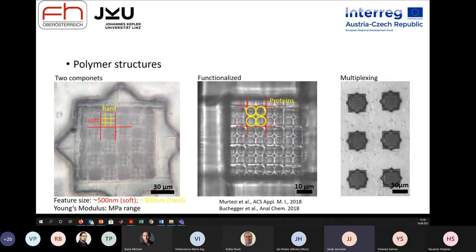So we were able to also vary the stiffness of the polymer. So we had hard lines and softer lines. How do we determine it? We determine it using nano-indentation via atomic force microscopy, or we also were mixing photoresist having functional and non-functional polymers, which means for us functional in this case were polymers which were capable of protein binding, and the red ones were inert.